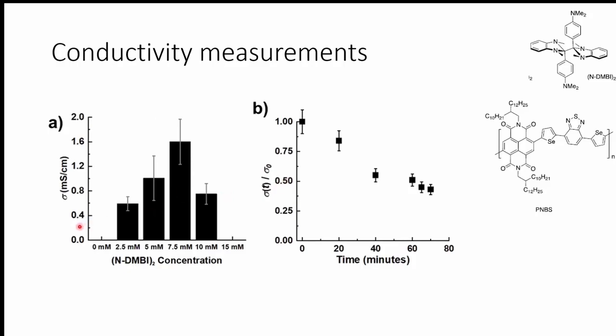When we measure the conductivity, we notice that at 0 millimolar, it's not conductive, because organic polymers have very low charge carrier density. The conductivity starts increasing up to 7.5 millimolar, which, if you remember, was the most crystalline film. So this was when all the stars aligned in these experiments. And then you get the maximum conductivity of around 2 millisiemens per centimeter.